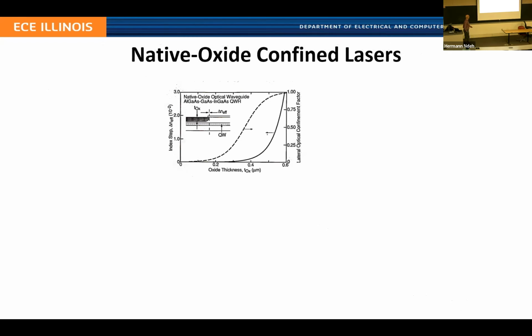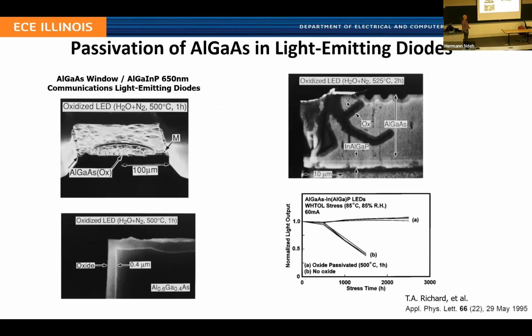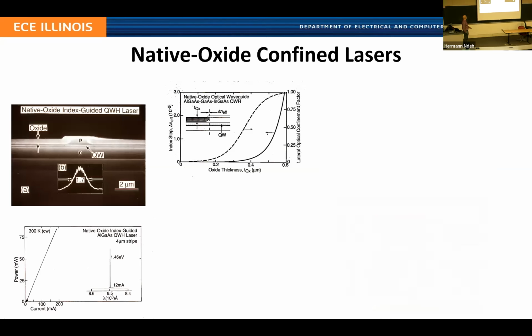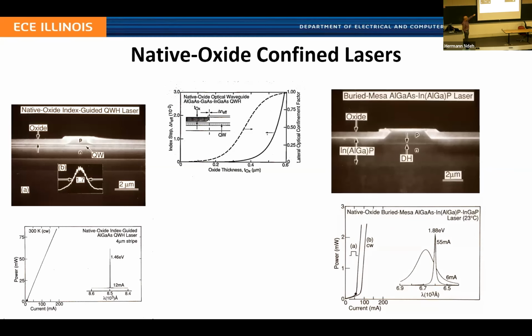The other thing that we came up with relative to using this new oxide was, could we use it to make index guided laser diodes? By making the oxide, patterning it next to a laser stripe and making it go closer and closer to the active region, we're able to take a significant index step for the lateral mode that would be guided by the laser. With that, we made index guided lasers using thick oxides in the AlGaAs system, as well as red emitting lasers in the aluminum gallium indium phosphide system.